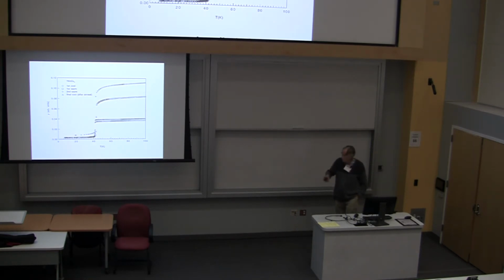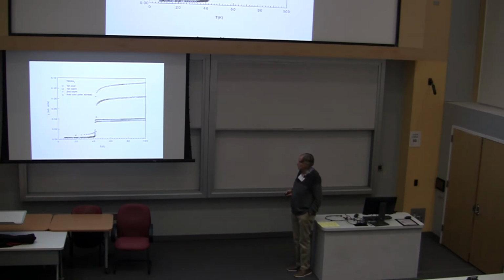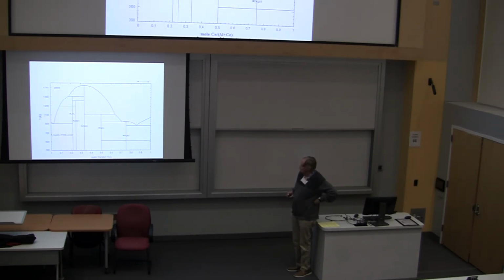But it turned out that someone was able to study this volume collapse, which is not a common situation. So it was actually a very nice system to work with. There's just a comment here. Because of this volume collapse, it tends to damage the crystals when you go through the transition. So when you cycle it, the resistance ratio changes significantly, and so you have to anneal and do things like that. And I'll comment a little bit more on annealing in a minute. You see, I'm about to run out of time here.